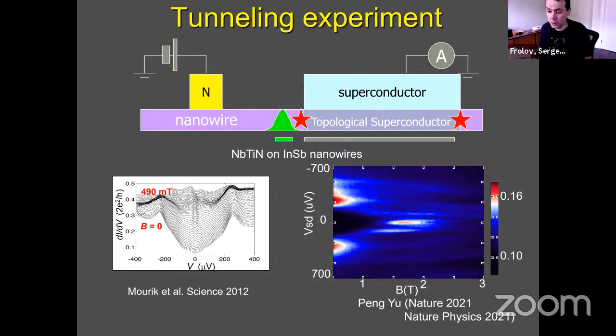And what kind of measurements do we do? Well, we do these kinds of tunneling experiments. We make contacts to this nanowire and we send current through. Majoranas are supposed to be located where these stars are, at the ends of the superconductor that we put down on the nanowire. We apply a voltage and we measure current. We tunnel across this green hump, which is a tunneling barrier. And when we tunnel, we get tunneling characteristics. In these, we find a zero bias conductance feature, a peak, and this has been predicted by theory to be a signature of Majorana fermions.